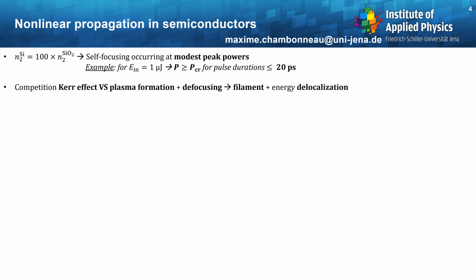To answer this question, one has to keep in mind that silicon is a highly nonlinear propagation medium. Specifically, when one takes a look at the nonlinear refractive index of silicon, it is 100 times higher than the one of fused silica, for instance, meaning that self-focusing will occur at relatively modest peak powers. Let me give you an example. Let us consider an input pulse energy of 1 microjoule, which is pretty typical for laser processing applications. Then the power will be higher than the critical power for pulse durations below 20 picoseconds, which is extremely large. As a consequence, there is a competition between Kerr effect on the one hand and plasma formation together with defocusing on the other hand. In other words, a filament is formed and there is energy delocalization.